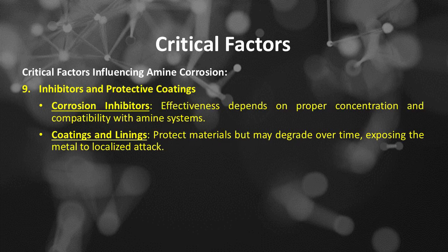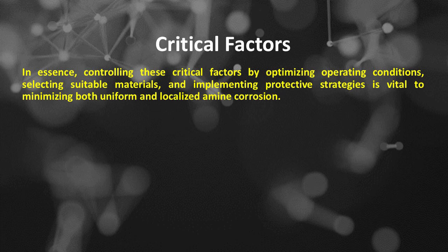Critical factors influencing amine corrosion. Number 9 is inhibitors and protective coatings. Corrosion inhibitors: effectiveness depends on proper concentration and compatibility with amine systems. Coatings and linings protect materials but may degrade over time, exposing the metal to localized attack. In essence, controlling these critical factors by optimizing operating conditions, selecting suitable materials, and implementing protective strategies is vital to minimizing both uniform and localized amine corrosion.